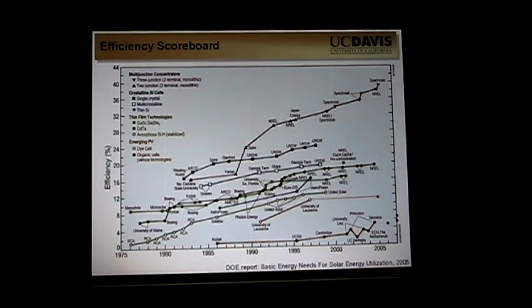Because really, the important number here isn't the number of watts that you can produce in a meter — it's the number of watts you can produce per dollar. As it turns out, roofs are cheaper. The technology that I work on is this one here on the bottom. The current record efficiency is right about 7%, about one-fourth as good as a high-quality silicon solar cell. But this technology is very interesting because there's the possibility to produce it for an order of magnitude less cost per unit — a factor of 10 cheaper. Over the last 20 years, efficiencies have gone from about 1% up to 6 or 7%, so this is a technology that's been developing very quickly.